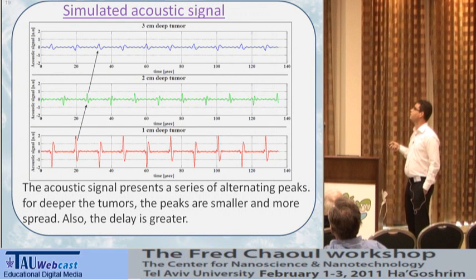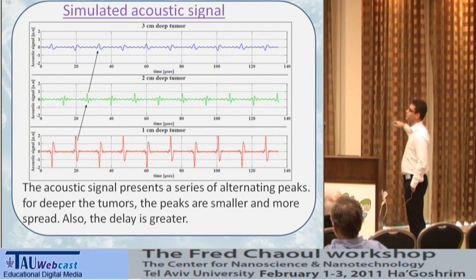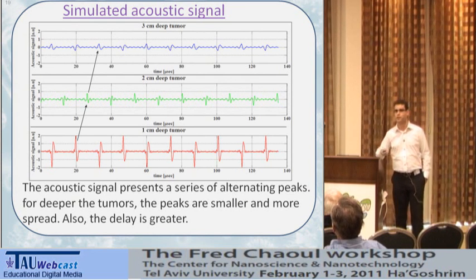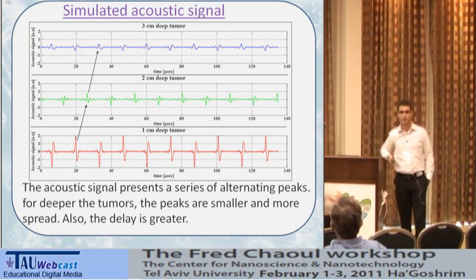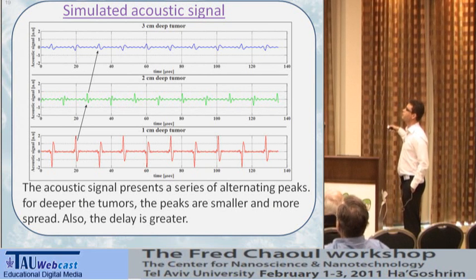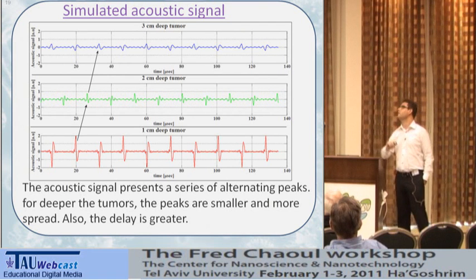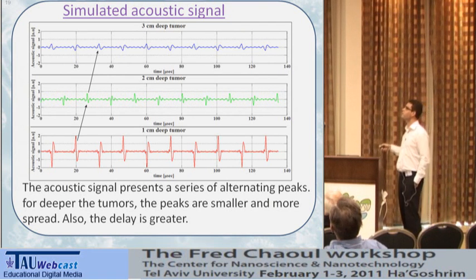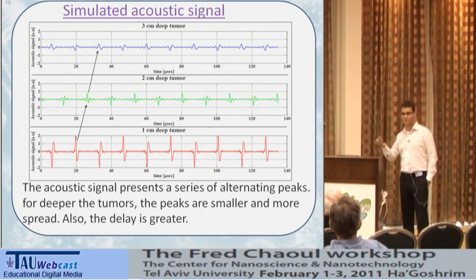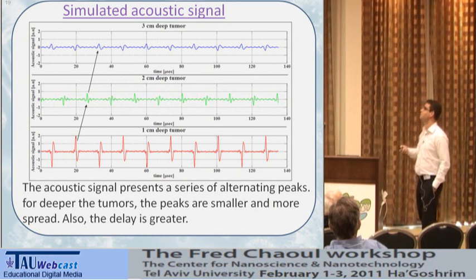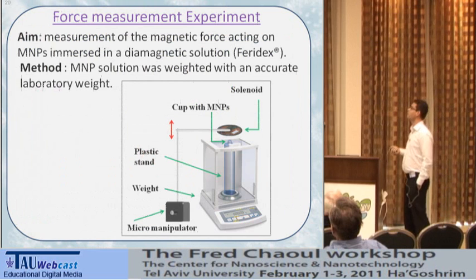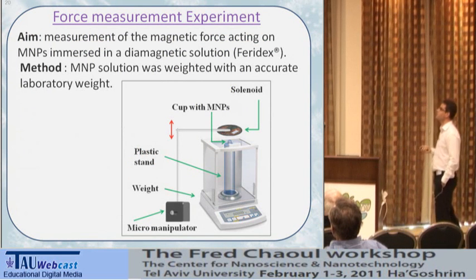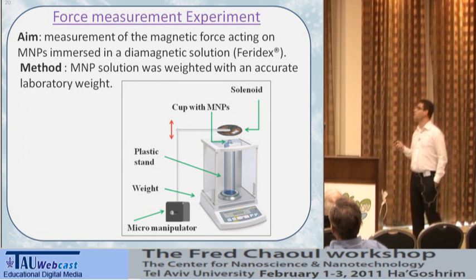And if we look at the simulated pressure wave picked up by the acoustic sensor, we see a series of inverted spikes, which correspond to the pushing and pulling of the nanoparticles. And we see that the deeper the tumor is, obviously the amplitude shrinks, and also the signal is smeared and delayed because it takes more time for the acoustic signal to reach the sensor. And we wanted to validate this model as well by experiments. We did a series of experiments. I'm going to show you only two.